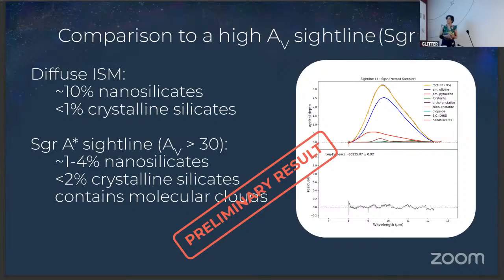So that's basically summarizing what I just said. So in the diffuse ISM, we find 10% nanosilicates and less than 1% crystalline silicates. If we look at the Sagittarius A star sightline, which we fitted back in 2004, we fitted it again now, including the nanosilicates. We find that we need, depending on the fit that we do, between 1 and 4% of nanosilicates. So here is Sagittarius A star. And the crystalline fraction is less than 2%. In fact, the value that I just showed you in the table was basically 1%. And this sightline contains molecular clouds.